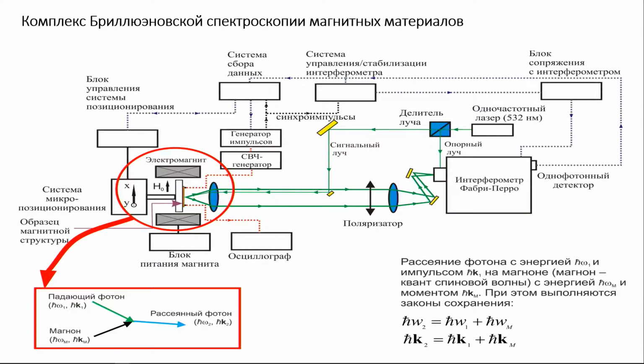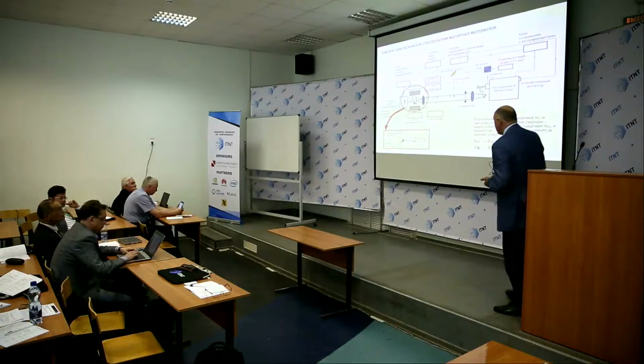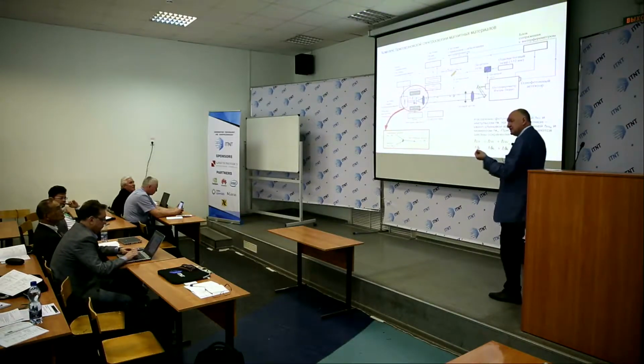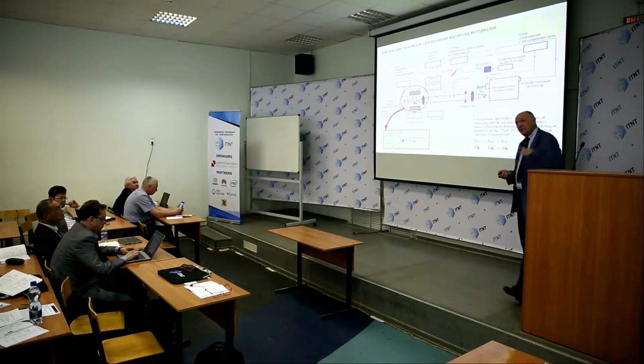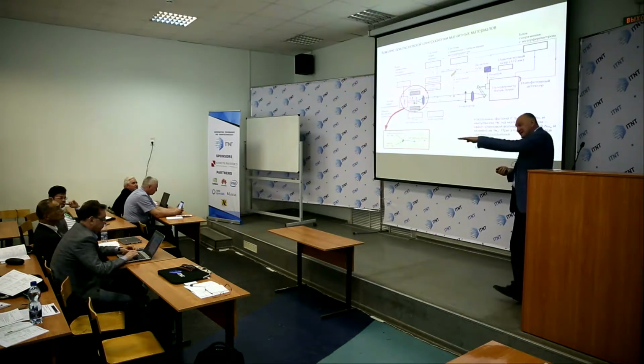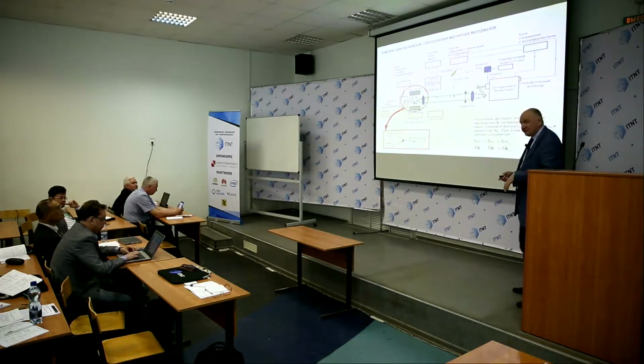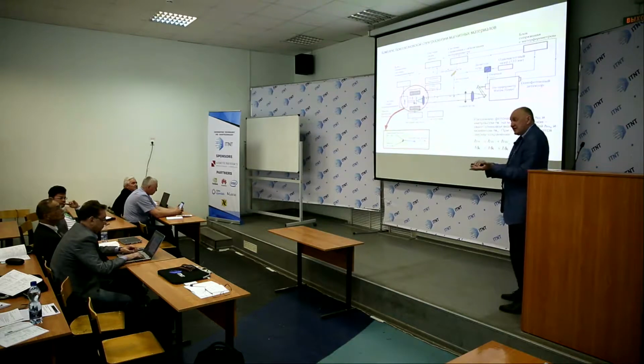So we have some electromagnetic wave which is falling on the surface of magnetic material. You have scattering by propagating spin waves, and you have scattered photons. When you measure the signal of reflected or scattered photons, you can see the frequency and intensity of propagating spin waves, and you can scan over the film surface. Therefore, you can build the structure of magnetic excitation in these materials.